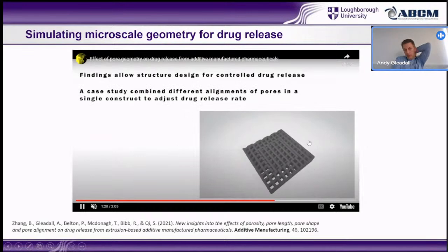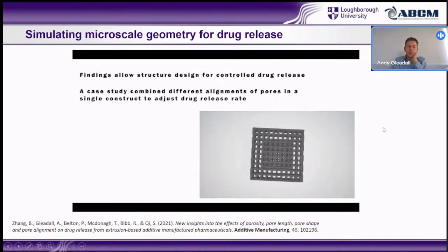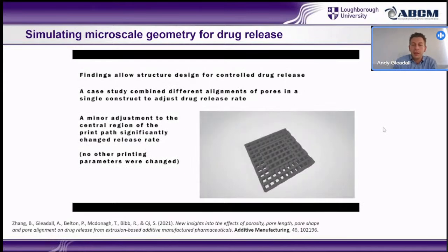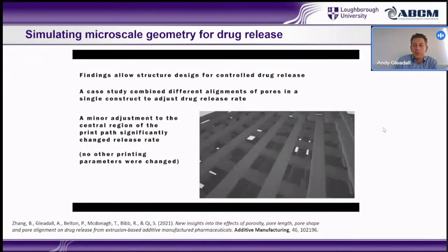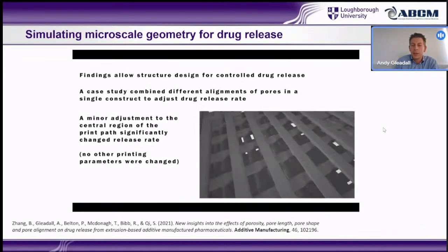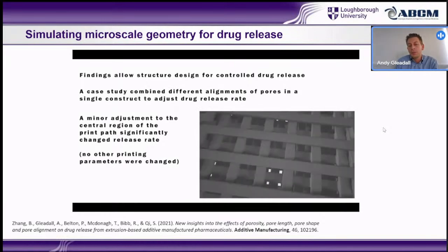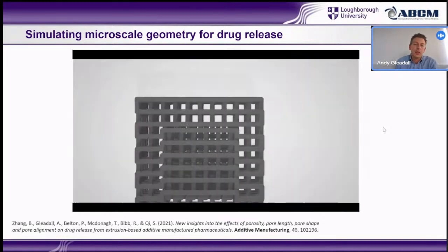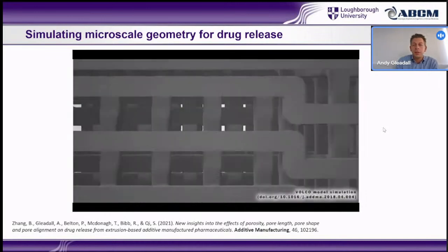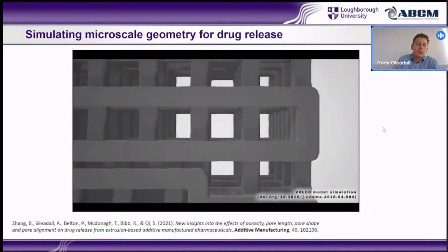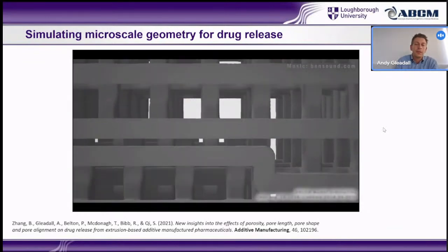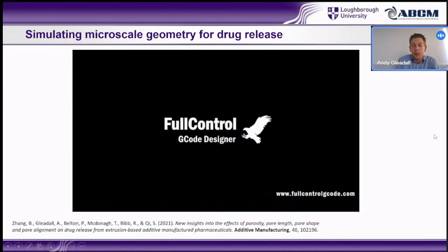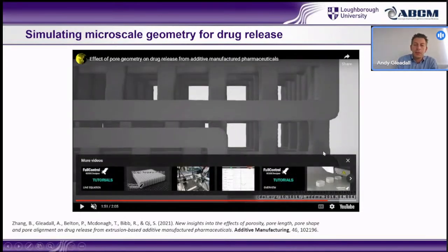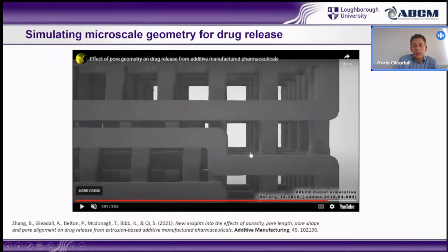So then a final example of it being used is for drug release structures. So we printed some tablets. This is just showing a rectangular specimen, but these were also printed in tablet form. And the drug was released from these structures, and we used Volco to simulate the actual 3D geometry and then get a prediction for the surface area and the porosity and how drugs would be released from these structures. And the great thing with Volco is it's just so simple and versatile for all different toolpaths. This was a slightly unusual print path to get different properties on the inside and outside sections. And it's just a case of sticking in different G-code to get the different predictions of the structures.